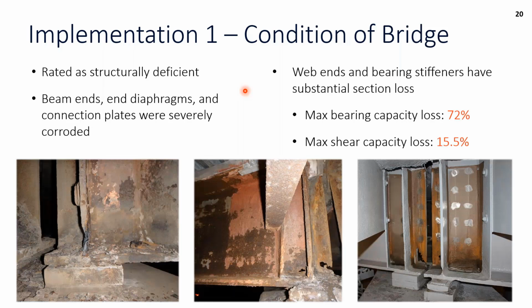So the condition of the bridge was structurally deficient, and you can see some of those full perforations in the web. And of course, these 2 pictures here are from the inspection reports. It only got worse once we went in and cleaned it. So I'm fairly certain this might be the same location, and you can see how big that perforation was after we went back and cleaned it. The beam ends, end diaphragms, connection plates, everything was severely corroded, and you could see we had really significant losses in bearing capacity, and we had some shear capacity loss as well.